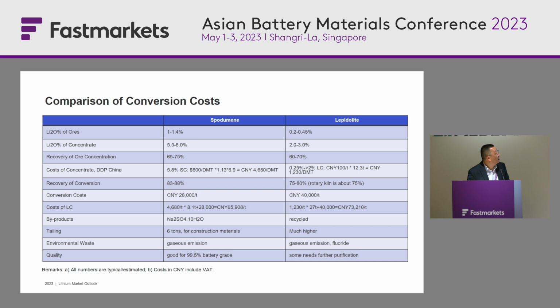And when you come to the cost of concentrate, that's my estimate, okay, basically it's 100 to 120 RMB from, say, the raw ores to the concentrate. So if you consume 10 tons of raw ores, that means your cost of concentrate is 1,000 RMB, okay? And by recovery of conversion, you can also see higher recovery in spodumene. Typically, we need 8 tons of spodumene concentrate to produce 1 ton of battery grade carbonate.